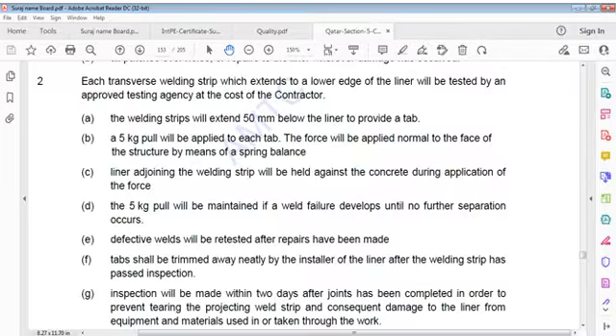Now, going further: the 5 kg pull will be maintained if a weld failure develops until no further separation occurs. Defective welds shall be retested after repairs have been made. Tabs shall be trimmed away neatly by installer of liner after welding strip has passed inspection. Inspection shall be made within 2 days after joints have been completed in order to prevent tearing of projection weld strip and consequential damage to liner from equipment and material used in or taken through work.